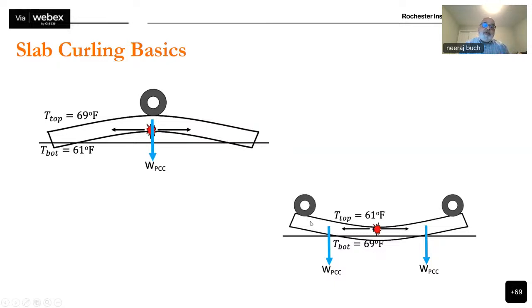When the temperatures cool in the evening, the reverse happens. That is, the top of the pavement is cooler and the bottom of the slab is hotter. So you have a negative gradient, and when you have a negative gradient, the edges of the slab lift off from the support, and you get this negative curl.